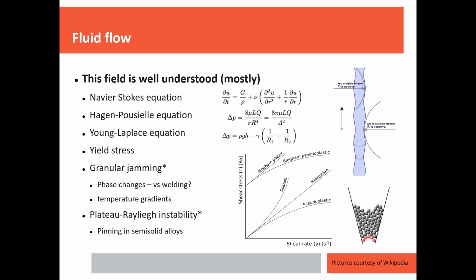We have the opposite effect in welding, where your material is liquefying and heating up as it's being removed from the wire. And that, I think, may be in some manner analogous to zeta potentials in normal fluids, where essentially your particle sizes are shrinking away from each other, and the interfaces between those particles are the most likely areas where melting will occur next. So the particles tend not to jam in a situation where the temperature is increasing, but in a situation where the temperature is decreasing, it's the opposite case. It's like these particles have an attractive force between each other that helps jamming occur. So that's definitely an interesting analogy to draw that really hasn't gotten much attention, and again, something worth researching.